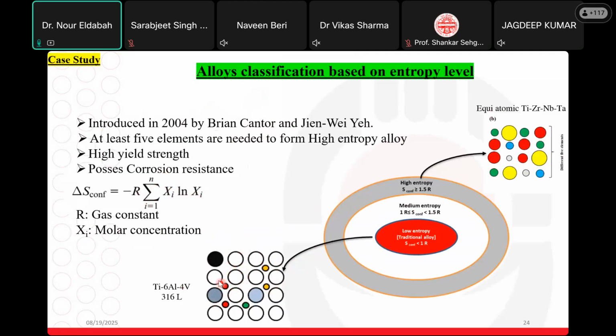So we have interstitial or substitutional additions to the alloy matrix. On the other hand, if we mix equiatomic concentrations of, for example, titanium, zirconium, niobium, and tantalum, you have no obvious matrix, there is lattice distortion, and different characteristics will be obtained from this category. So we have low entropy, which is the traditional alloy, high entropy alloy, and an intermediate category, which is medium entropy alloys.